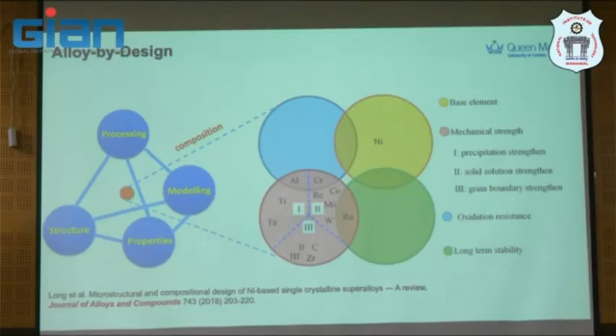But the most important thing for superalloy is actually high temperature property, with the various strengthening mechanisms that you have. If you talk about aluminum, titanium, tantalum, these are gamma prime forming elements, and this will go on to form gamma prime, the secondary phase. So nickel-based superalloy is a two-phase material, gamma and gamma prime. You can think of it as a composite if you are working in the composite area. And this gamma is a softer phase than gamma prime. It's kind of like a carbon fiber composite, so it gives strength to the material.